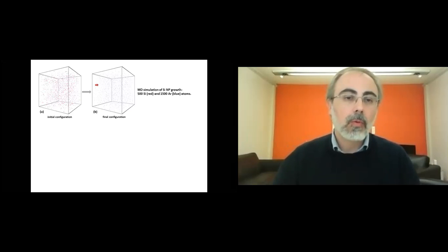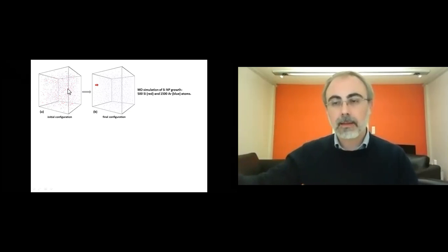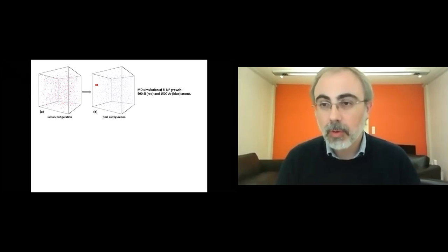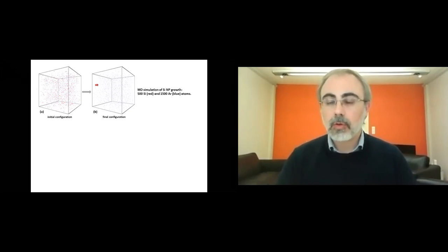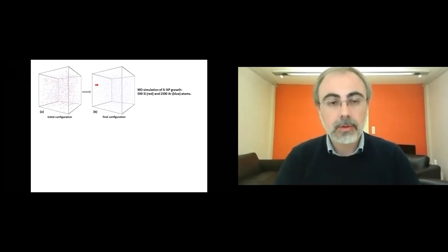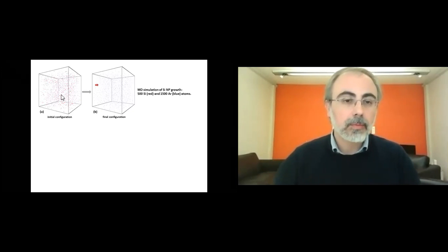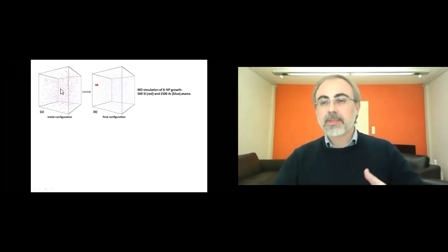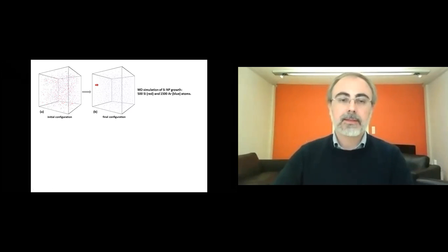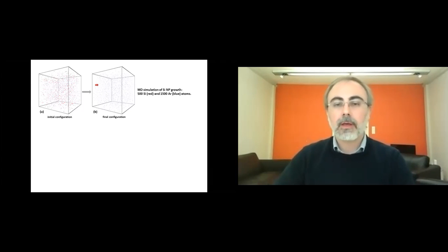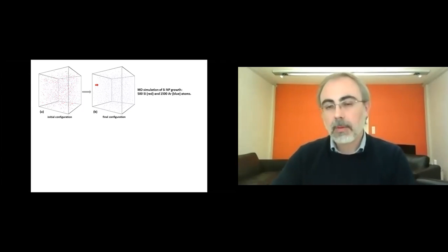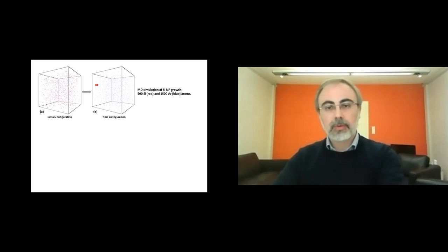So every time one argon atom leaves the box from one side and enters on the other side, its temperature is reset to a specific temperature that we want to use. In most cases, it's room temperature, because all this process happens at room temperature. So every time an argon atom goes through the periodic boundaries, it represents a new atom which now has the temperature of the whole chamber, which is more or less room temperature.